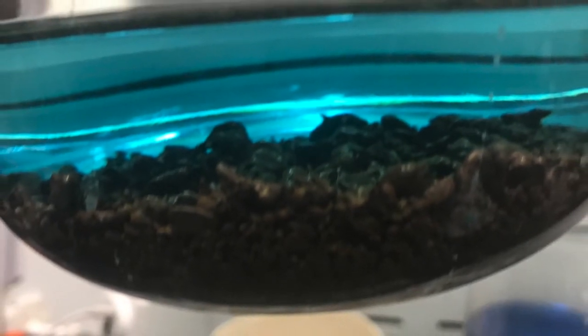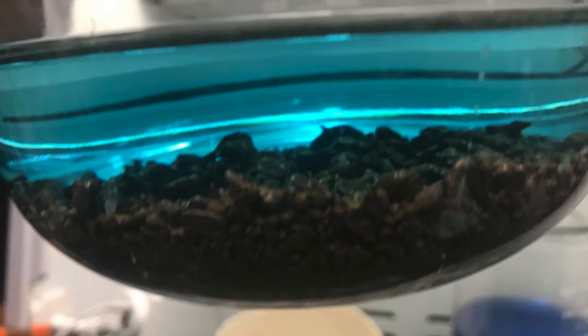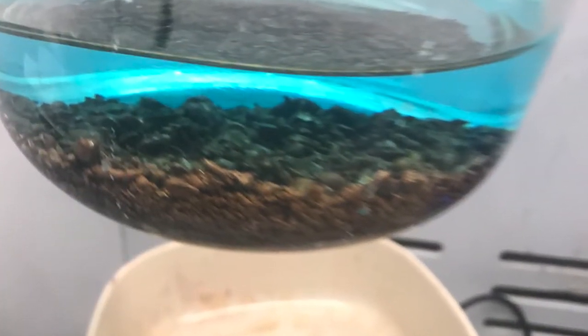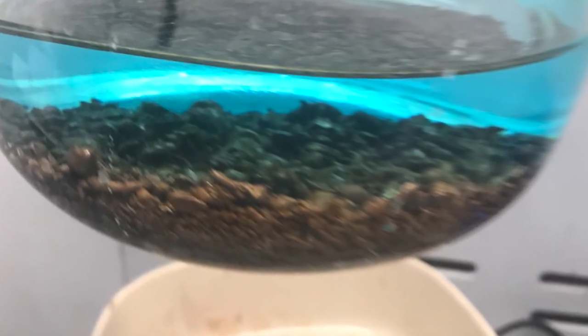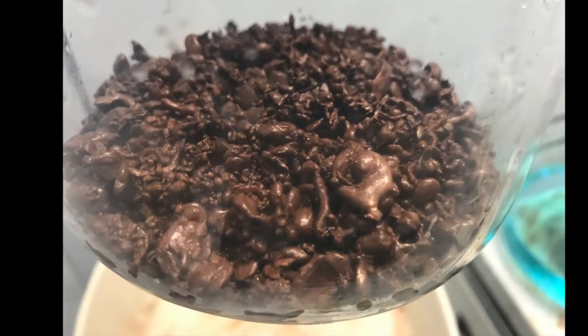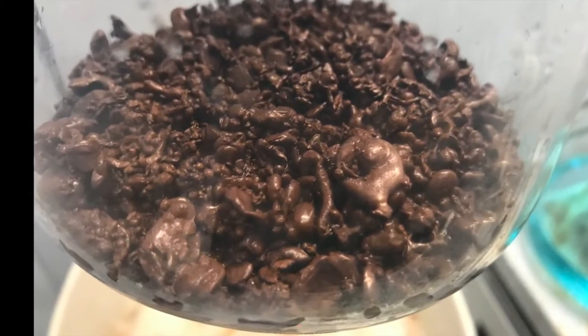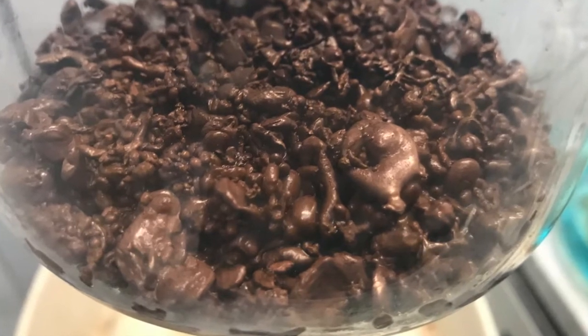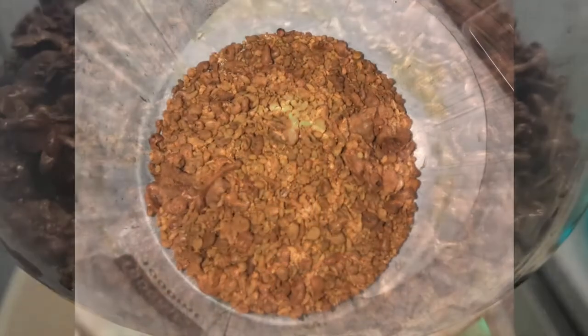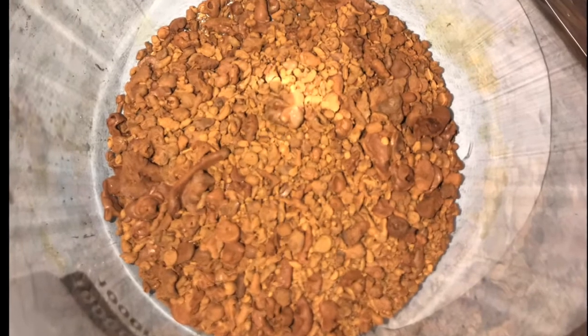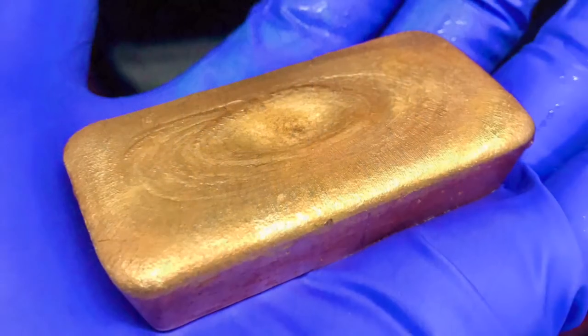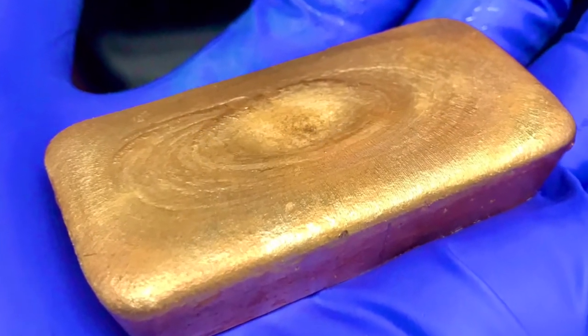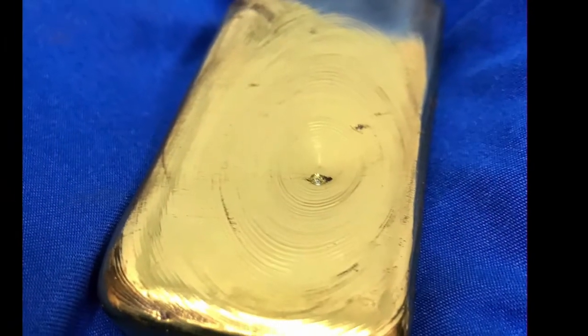And this is the honeycomb of nearly pure gold that is left after the impurities have been leached out with the nitric acid. That gets washed up and cleaned up, and as much impurity taken out of it as possible, which should leave it at about 98% pure. That's very pure right there, and that produces a very nice bar like that 20-ounce bar there.